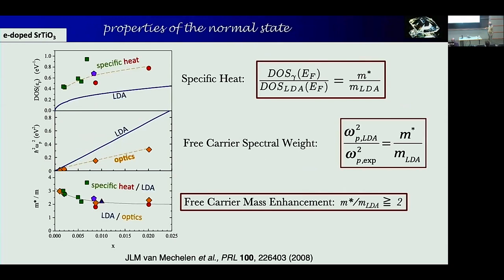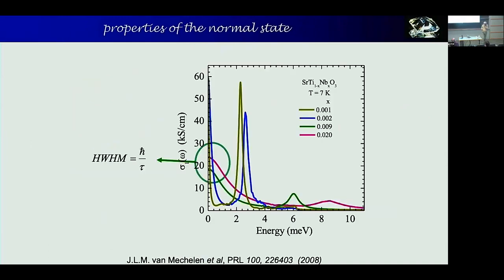And so that gives you two different estimates of the mass enhancement, one coming from specific heat, the 2 points that I just showed you, other points from the literature also, and then there's a number of points that actually use this, which ones are those? It's probably the two red points, I forget, that actually come from the optics. So the optics and the specific heat give basically the same information. Your effective mass is twice as big as you would calculate from this band structure calculation that you just showed.